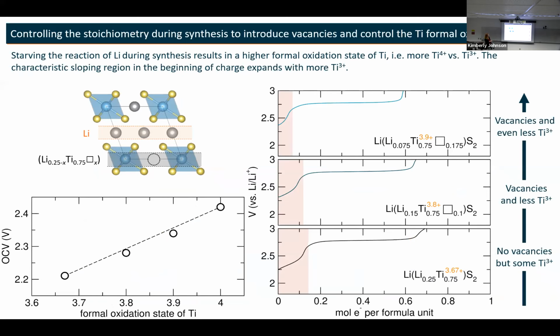Yeah. So the way that we make these materials, first we check the structure to make sure it is this sort of disordered rock salt phase. And if that's true, then we can assign a 2- formal oxidation state to the sulfur, because we have no sulfur-sulfur bonds. They're all bonded to the close packed lattice. So we checked that, to make sure that's true. So we see no charge compensation by the sulfur as a result of the substitution. I see, so any electron transfer is only between the cations. It's not involving the sulfur, is that correct?